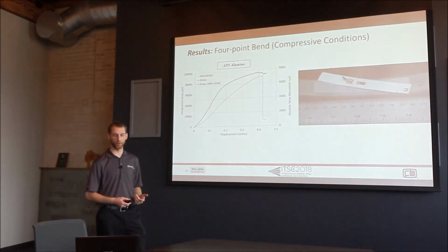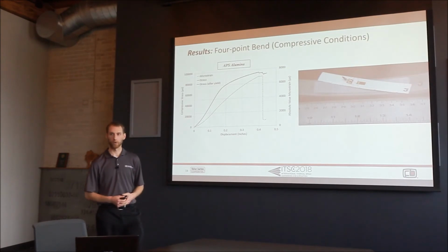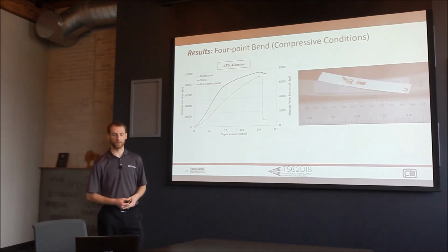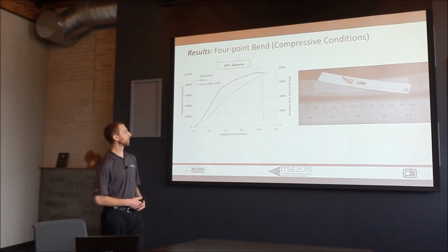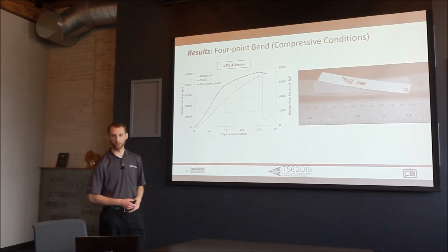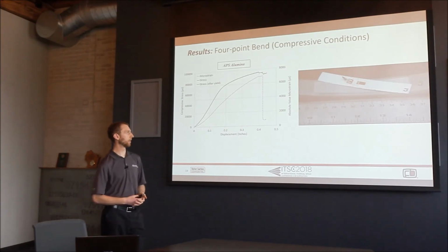Now we did one test where we flipped the bar to put the coating under compression, and this is one example of when we do completely lose adhesion, basically the drastic drop in strain there at about 0.4 inches. That's when the coating completely flaked off, and that's what the example would be if we did lose coating adhesion.